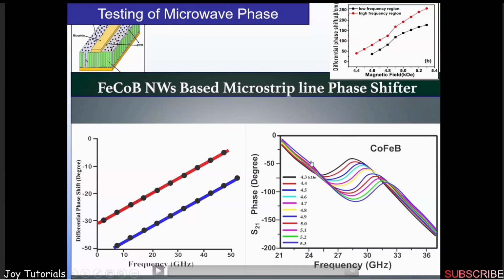So what we choose is the lower side of the stop band and the higher side of the stop band. The insertion loss, the design parameter for practical applicable devices, should be less than 3 dB. 3 dB means half of the power is lost. So if it is used for a phase shifter, it should be less than 3 dB. What I plot here is the low frequency and high frequency range of the phase shift. You can see the phase shift going from some 50 degrees towards 250 degrees at the lower side and at the higher side. So this is the testing of the phase shifter.